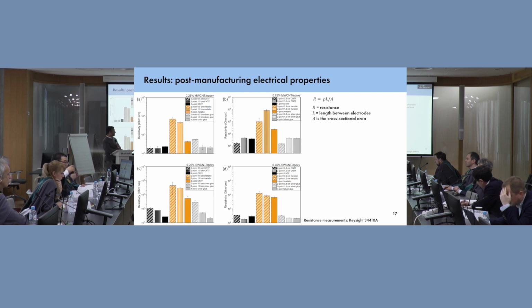Now, across the board, again, we see very similar results when it comes to our carbon nanotube fibers. Within variance, in most of the cases, but in some cases, outside variance. And we have a limitation on equipment in this case, but again, this can be discussed in the discussion section. For the metallic embedded electrodes, we have a much higher reading, like 1 to 2 magnitudes easily higher, and a lot more variance.